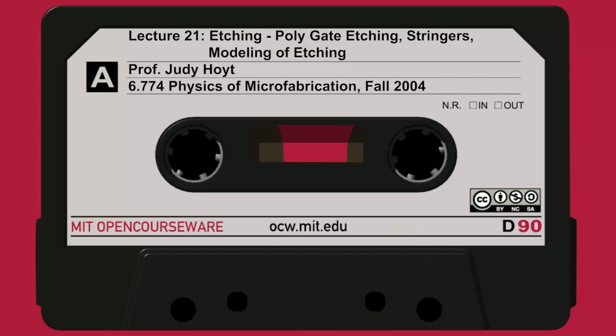It just gives you time to get the old gases purged out from the prior etch, which was the breakthrough etch, and get the new ones purged in, and establish your pressure of 10 millitorr. Then you actually do the main etch. So here you turn the plasma on by turning the power onto the top and bottom electrodes. So the plasma is now lit, and you're actually etching here for a time of, in this particular example, 60 seconds. So you etch by time. So it's a 60-second etch.